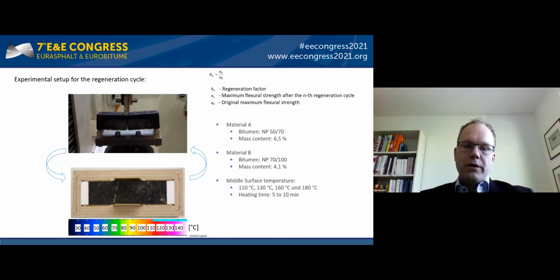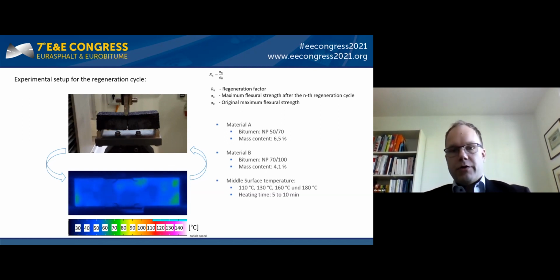So what experiment was carried out to show how the regeneration affects the asphalt? A three-point bending test on 4x4x16 centimeter prisms was carried out. Five regeneration cycles were carried out. After each three-point bending test, with open cracks, the prisms were placed in PTFE molds with some wooden frames around them to heat them up and reshape them, as already explained in the regeneration process.